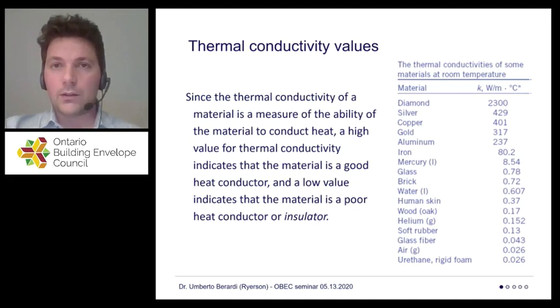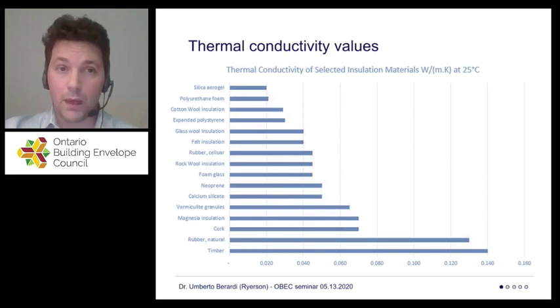And more in the building sector, we are seeing an introduction of new products with thermal conductivity of 0.01. So we're getting to values that are extremely low, and the lower these numbers are, the more we need to be careful in trying to understand what that very small number means. Just to report again what I was saying in a more graphical sense, these are the thermal conductivity values of a few selected insulating materials we often use in buildings at the temperature of 25 Celsius. You see that we can have some fiberglass typically standing in the range of 0.04. We have highly insulating products these days getting popular, aerogel, vacuum insulating panel, all these kinds of new materials with a thermal conductivity below 0.02, and a lot of wood materials in the range of 0.1. So this is more or less giving you the variety of these numbers.